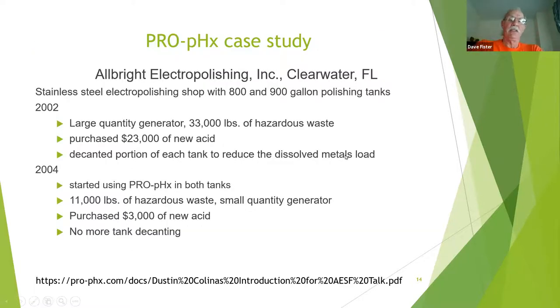This is one of the better case studies. This is Albright Electropolishing, Clearwater, Florida. They're a stainless steel electropolishing shop, two tanks, 800 gallons, 900 gallons. Electropolishing takes a lot of metal off of parts, so you are getting a significant amount of metal buildup fairly rapidly and you're consuming acid fairly rapidly. So in 2002, these guys were large quantity generators at 33,000 pounds of hazardous waste. They purchased $23,000 worth of new acid that year. They were always decanting portions of each tank to remove some of the dissolved metals load and adding back with fresh acid.